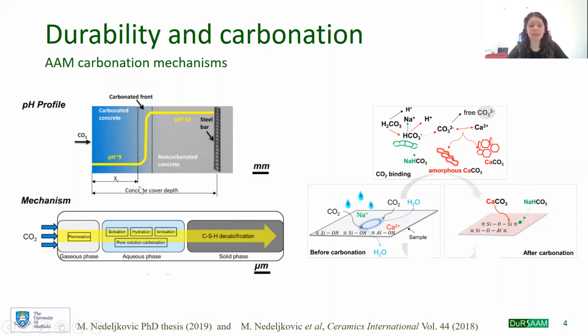And you can see here that what we call the carbonation front is where the pH drops. We call it the carbonation front, and it's really important because it is when the steel bar can be corroded and is not protected anymore by the high pH. So that's what we want to avoid.